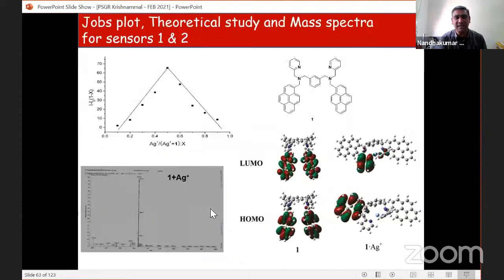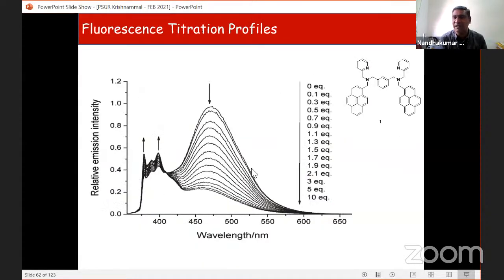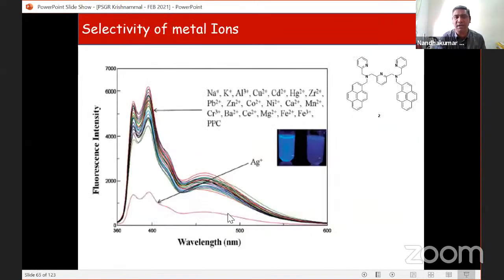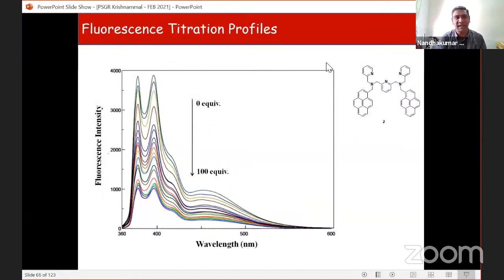Previously, this type of mechanism we call ratiometric sensing. So you have an isoemissive point here, and this can be converted into quantitative measurements. When you have an isoemissive point, it is because one peak is going up and the other is coming down. But in this case, it is only quenching. Even the monomeric and the dimeric, excimeric, both are quenching. There is no isoemissive point, no one enhancement and one quenching, just a change of one nitrogen. So the mechanism is entirely quenching. Just the introduction of one nitrogen changes the total mechanism. But luckily, both are for silver.